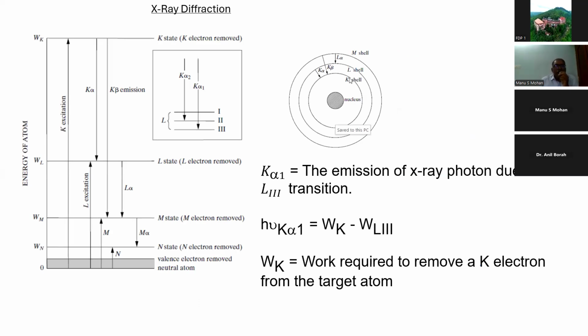So now comes the emission, and what is K alpha 1, what is K alpha 2. Suppose the K shell is n equal to 1, the L shell is n equal to 2, and n equal to 3 gives the M shell. From the K shell, if you knock out an electron — you saw that in the copper target, when the electrons from the tungsten filament strike, if a K shell electron is removed — and from the L3 subshell...